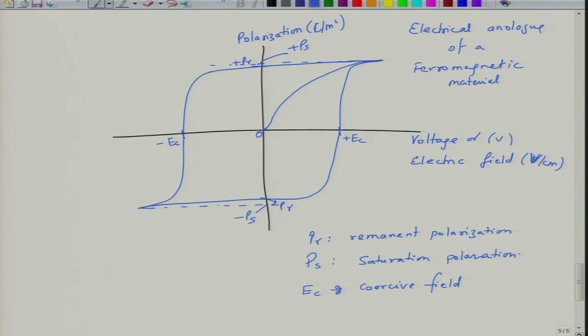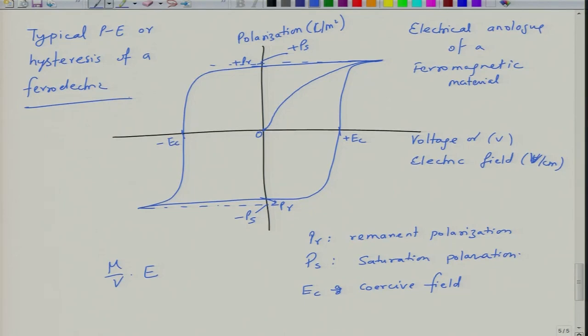The area under the curve is essentially the energy, the product of P and E, which is nothing but mu divided by V into E, and this is nothing but the energy density. So it is the energy that is spent in the process of switching. We will see the mechanisms of why this happens, but this is a typical PE, or hysteresis curve, of a ferroelectric. If a material is ferroelectric, it will show a non-zero polarization at zero field, and the polarization is zero at some finite field, and this is a stable effect. The most important thing is this is a stable effect. It remains stable for a long time.